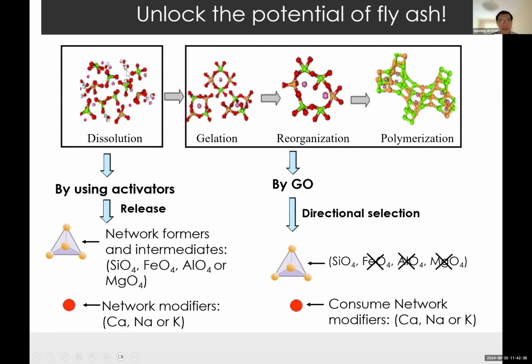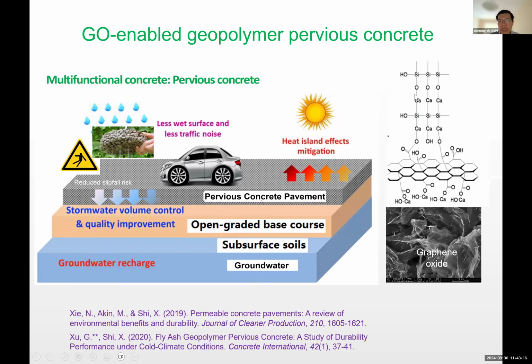So the first one is the fly ash is the inorganic polymer, so you have to dissolve it. So we use activators such as waterglass and calcium chloride to help dissolve it. Now, once it's dissolved and reacts with water, you form the new gel. Because of the presence of these nanoplatelets, they're like coaches. I would say originally without graphene oxide, it's like a soccer field with random players. Now with coaches, they're more organized. So they're reorganized into teams, and the final product is much higher degree of polymerization and more regulated microstructure. So now that's basically the patent itself, to develop a clinker-free cementitious binder from fly ash particles, fly ash industrial byproduct.